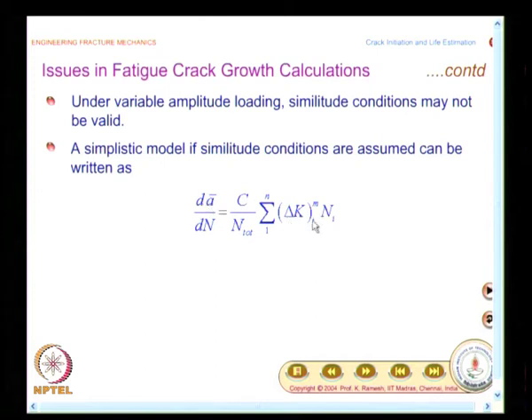And I have different cycles. I have delta K is a function of the cycle also. So, what you have is, you have different amplitudes, and for each one of the amplitude, you sum it like this. You have it as delta K_i power m multiplied by n_i, and I have total number of cycles as N total. From this expression, you would be able to get the average crack growth rate. It is an approximation. We will have to verify how good this approximation is valid in the context of your given problem.